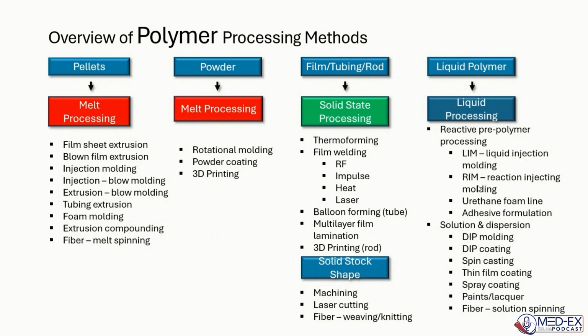Okay. And in liquid state processing, there are two basic kinds of liquid processing. First is really either a pre-polymer or a reactive monomer itself, where you can finish off the reaction. Those are high viscosity materials, especially silicone, used in liquid injection molding or reaction injection molding. Those processes fall under liquid processing, and they use thermoset kind of chemistry.